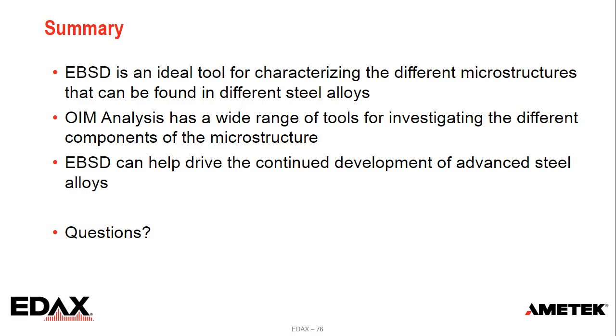Here's a question: are there some measures to improve the image quality of the deformed sample in EBSD? Yes, there are. Defining improvement is a little tricky. For all cases, sample prep is really important. You want to at least make sure what you're measuring is as representative of the true sample as possible. So the best sample preparation will help improve your image quality, and then any decrease in image quality corresponds to the true microstructure. If you have a deformed material, your image quality will be less than if you had a recrystallized material, and you want to be able to tell that.